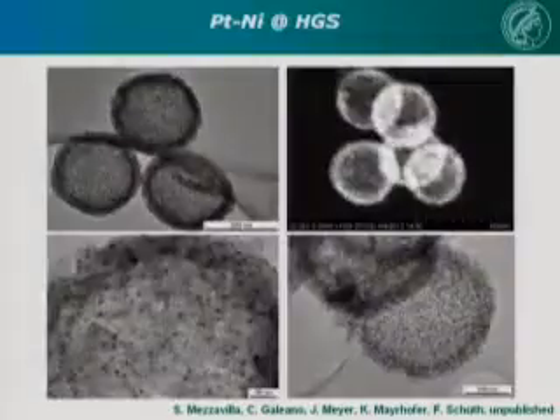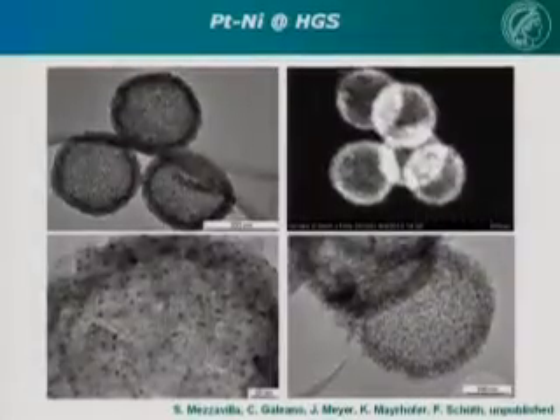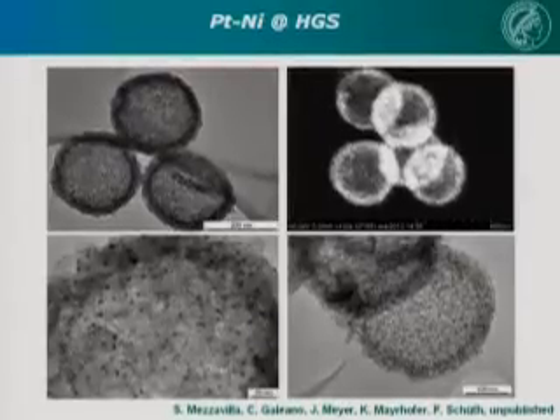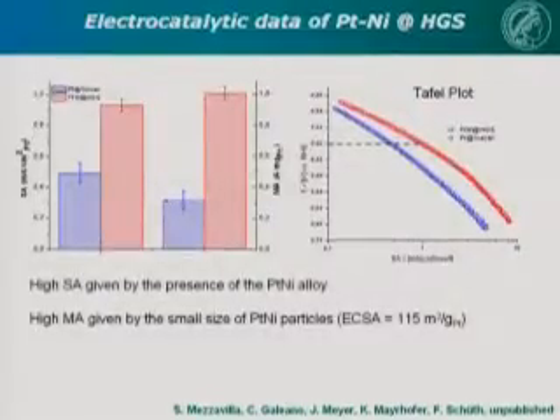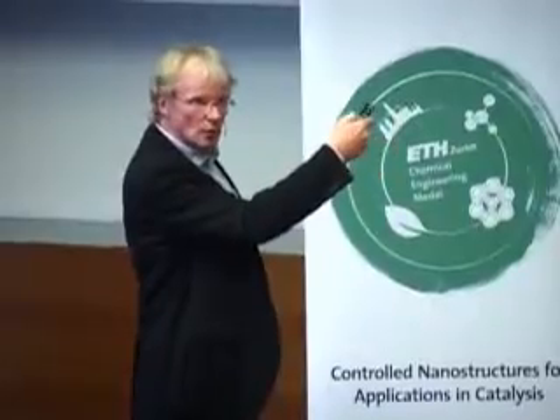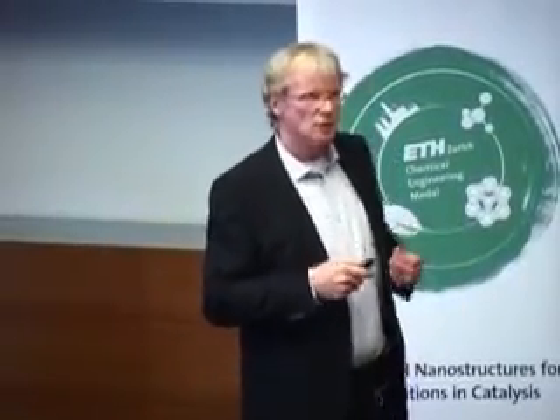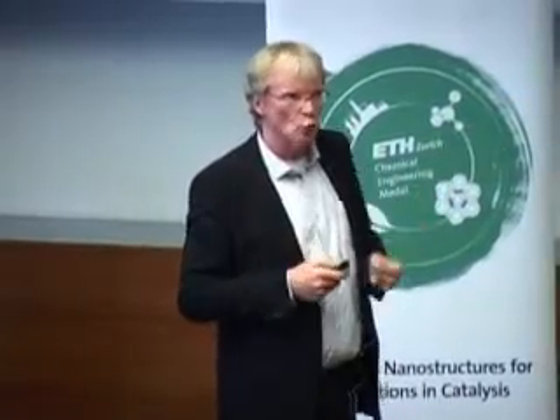This is the protocol we don't need to discuss in detail, and it actually works. If we treat at high temperatures, you see here the sizes. These are the alloy particles, size 2, 3, 4 nanometers. And the most important benchmark is then the electrocatalytic test. This is pure platinum mass activity. This is the platinum-nickel alloy. So we get a roughly 3-fold increase of the catalytic activity of this catalyst. And with this system, we actually meet the benchmark specifications of the US DOE for commercializable fuel cells.